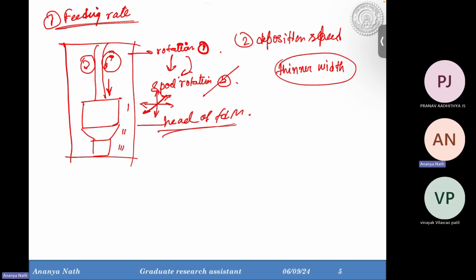When you get thinner deposition width, I repeat, when you are moving your head at a very high speed, but the melted metal or melted polymer coming out of the nozzle is not enough to get deposited over the build plate, this will happen over the build plate. This is the nozzle, this much volume of material should come, but it is moving at such high speed that it is getting thin, and this is the thinner width of the track. Okay, so this is one case.